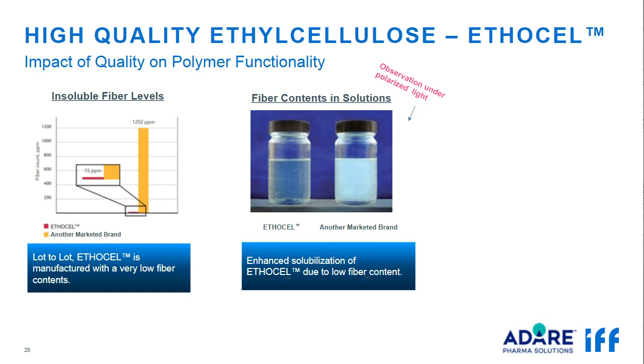We've done a quick experiment to show the impact of insoluble fibers. In a low concentration solution of cellulose, fibers are optically transparent to the naked eye and don't give any indication of their presence. But under polarized light, the suspended fibers in high concentration solutions scatter light and make the solution look turbid. This picture shows 15% solution of cellulose in organic solvent under polarized light. Ethocel solution is on the left, and the solution of the other brand of cellulose is on the right. The right sample is more turbid, indicating higher level of insoluble fibers.